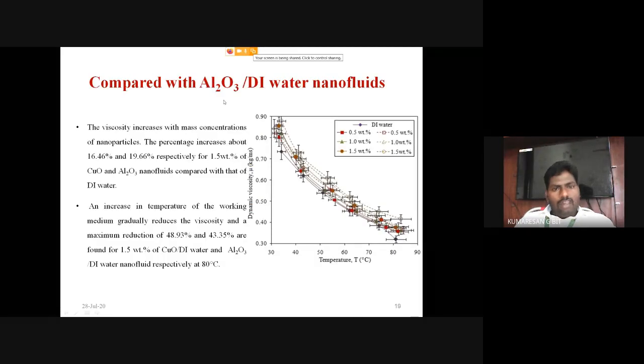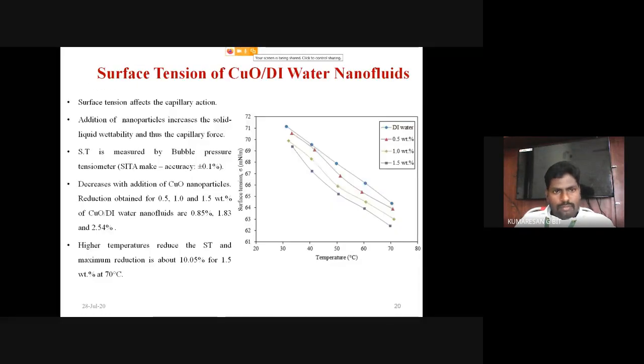That value is compared with the aluminum oxide DI water nanofluid. Then aluminum oxide DI water nanofluids attained low viscosity as compared with that of the CuO nanoparticles. This is because of the density of the aluminum oxide nanoparticles. It is almost 50% lower than that of the copper oxide nanofluids. Then surface tension. Surface tension is one of the important parameters when we are studying about some flow characteristics of any working fluid.